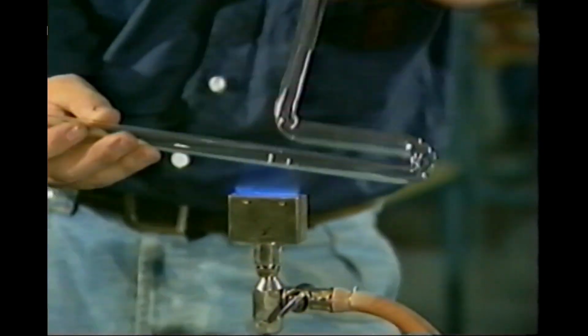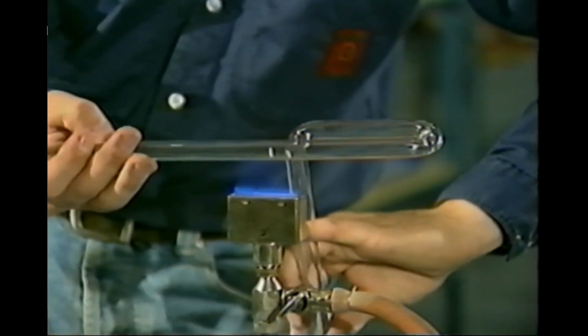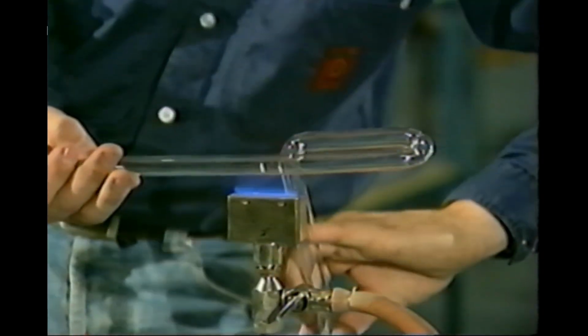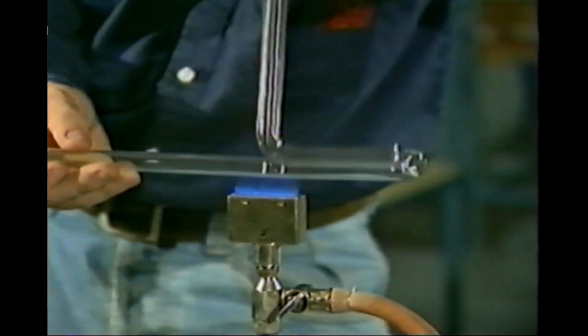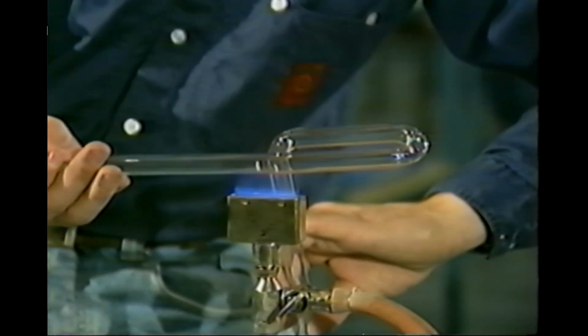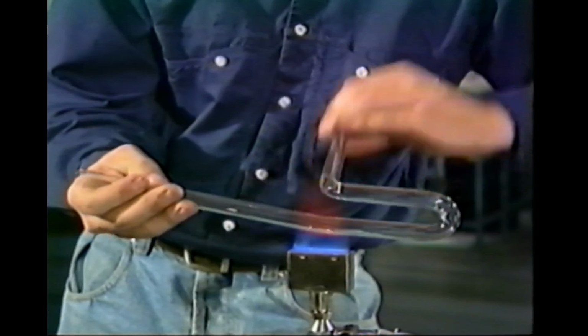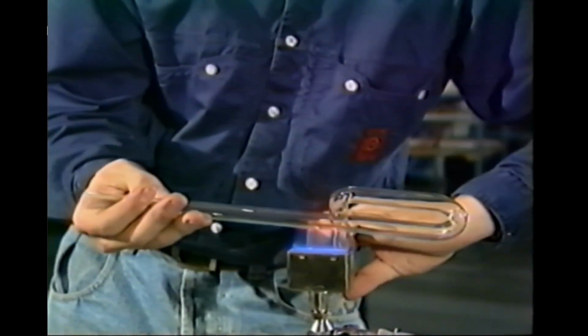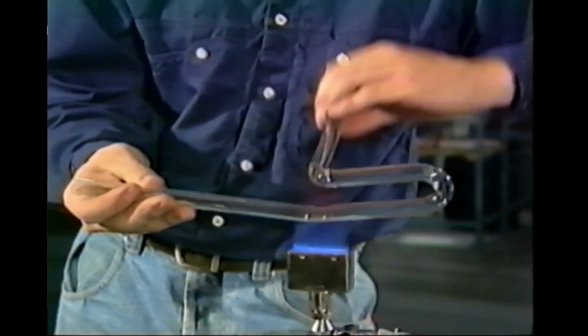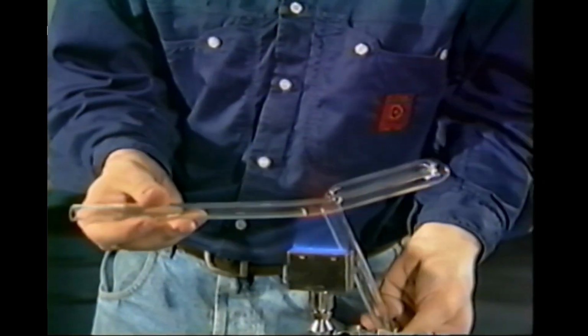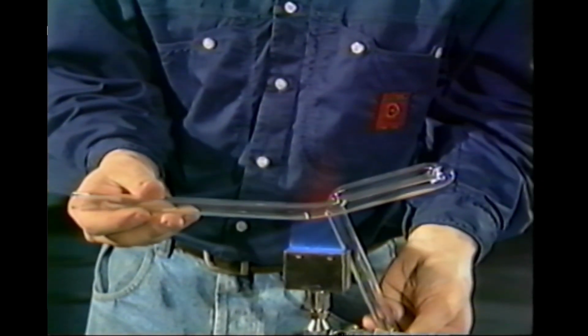The glass must be fully rotated back and forth, with the mark position in the flame off-center for this melting operation. Because this is almost two bends performed at the same time, the pencil mark must be offset in the flame. The area of melted glass should be approximately 2.5 tube diameters. When the melting glass glows bright orange, cease rotation and again give the area opposite the pencil mark extra melting. To bring this area into the flame, it is necessary to flip the glass over.